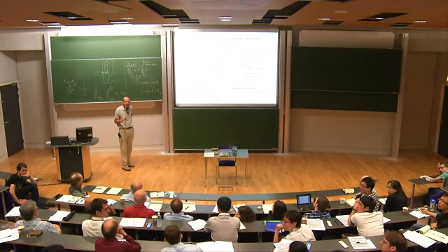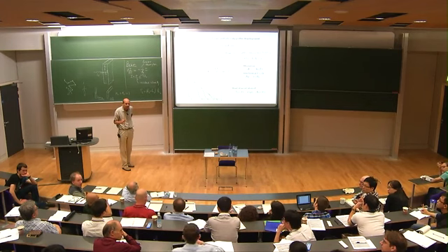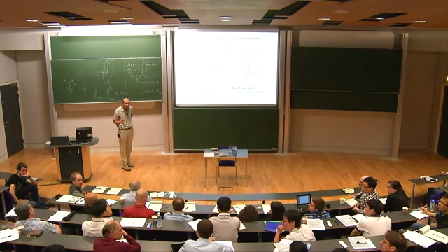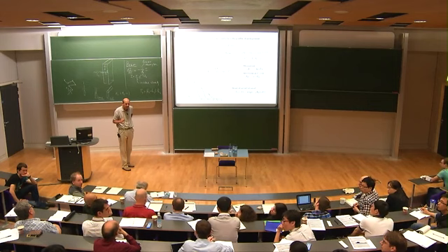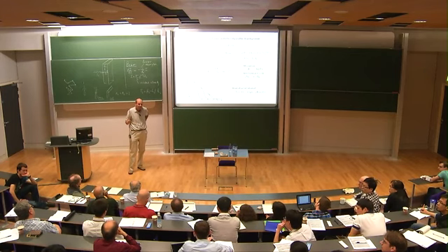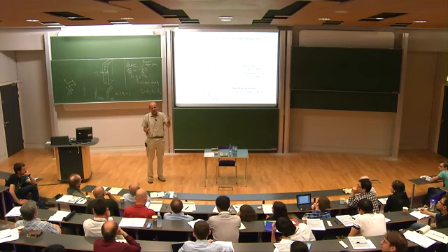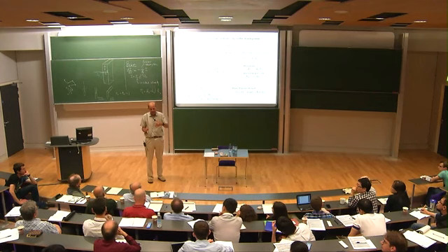The assumption you use of deformation at constant volume, I was just wondering, so that's pretty good for rubber. How good is it for a nematic elastomer? I mean, you'd expect some small change in volume. Is it 1%, less than 0.1%? It's the sort of volume change that you have when you go from the nematic to isotropic state in a conventional liquid nematic.